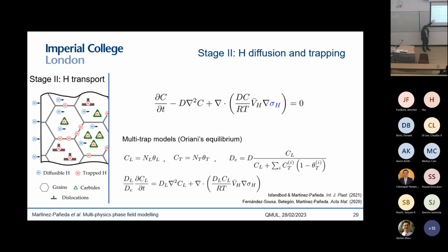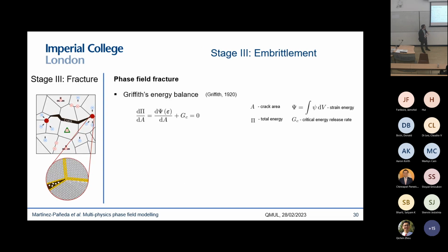So we have implemented numerical models or theoretical models, based on thermodynamic equilibrium, that can characterize how the hydrogen distributes itself between the lattice and trap conditions. And for example, very often we're interested in what is the concentration of hydrogen on the grain boundaries, because it could be a weak interface. But with these models, we're able to quantitatively know where your hydrogen is. And once you know where your hydrogen is, then you need to model this embrittlement process. And for that is where we use the phase field model that I showed you before.